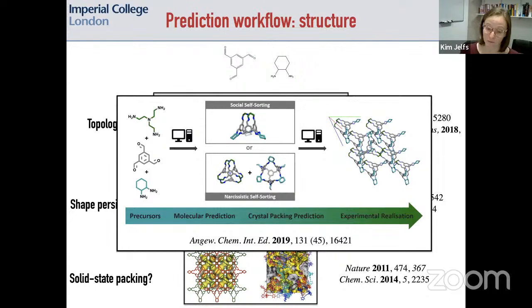At that point, we then went with Graham Day and predicted the crystal structure packing, while those doing crystallography worked on crystallizing the systems experimentally and getting the structures as well. And we found from that we were able to pick up all the key features that you would get in the end, in terms of the preferred packing modes, porosity, and whether you get homochiral or racemic systems, because the molecules have intrinsic chirality, generally speaking. So that for us was a really nice example of how we can put all of that together. It's certainly not trivial, but really important to work directly with experiment there.